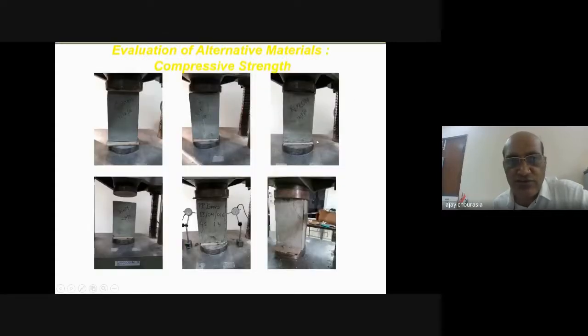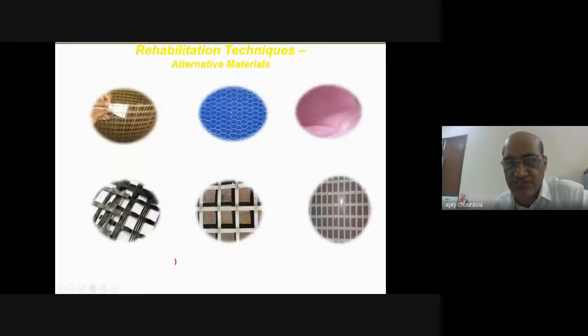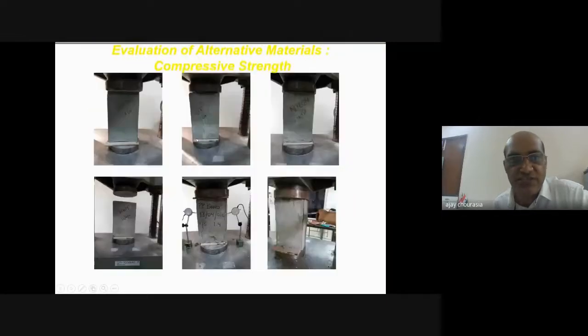Later on, the specimens were jacketed using all these 6 different options, embedded within a plaster of 15 mm thick, 1:6 cement sand mortar, 1:4 cement sand mortar, and then subjected to uniaxial axial load. The response was measured in terms of load carrying capacity, crack pattern and volumetric expansion in both directions to know the different engineering properties.